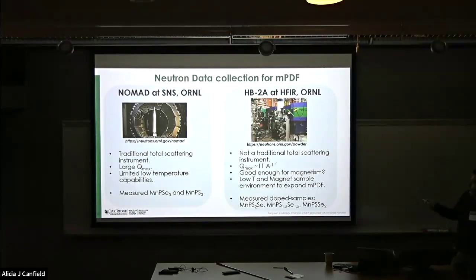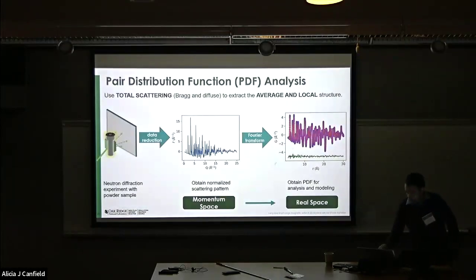So we also use this instrument, HB2A, and this is not a traditional PDF instrument. It has a limited Qmax. But if this is good enough for magnetism, then we can start to use the more complicated sample environments and look at the materials in a different way. So the data is just collected the same way that you would do any diffraction measurement. You put your sample in, you powder sample, you get a diffraction pattern in reciprocal space, you correct for background if you can, and so forth, and then you just perform the Fourier transform and get your PDF signal in real space.